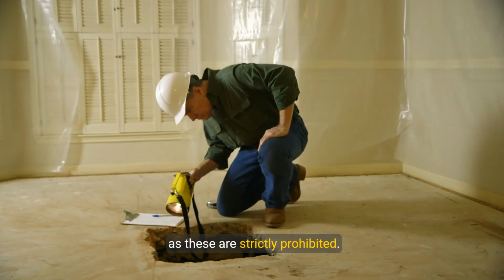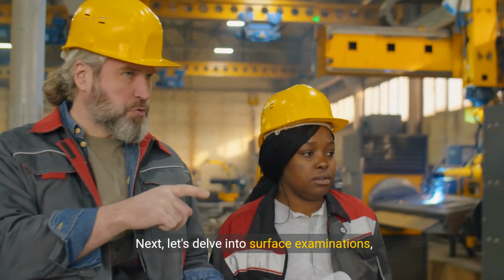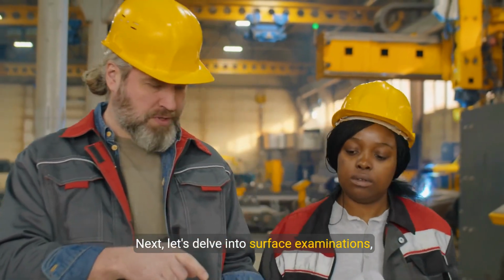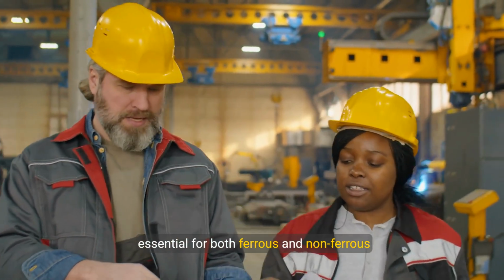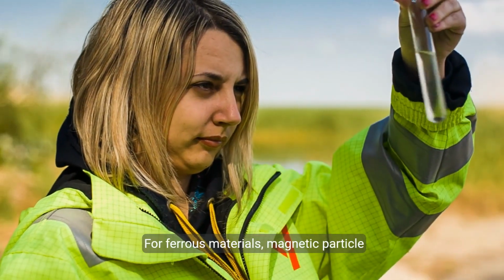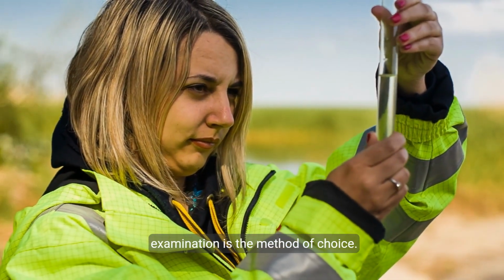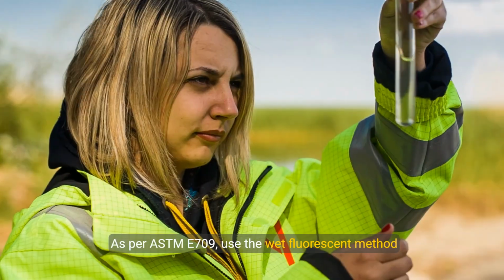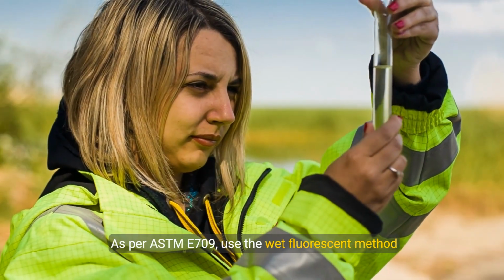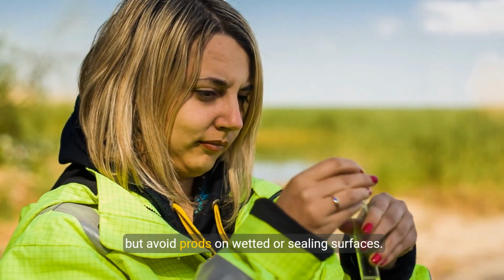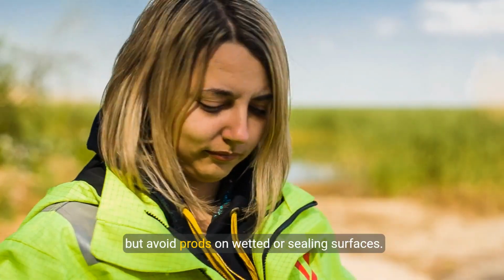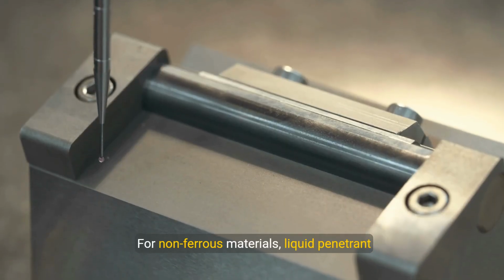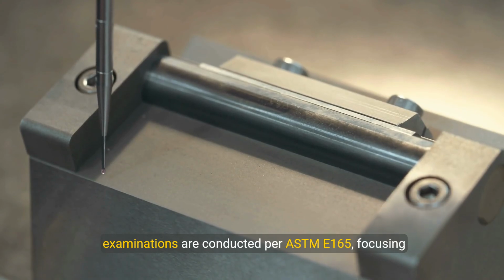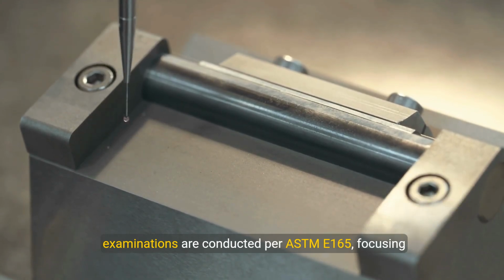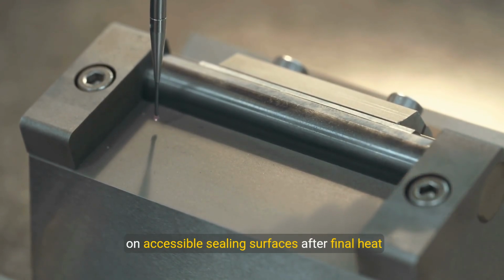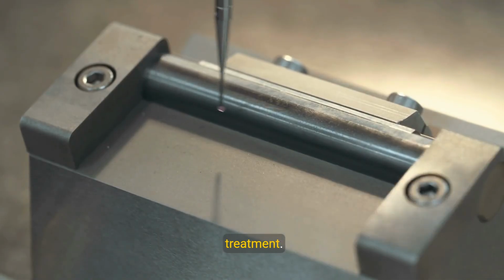these are strictly prohibited. Next, let's delve into surface examinations, essential for both ferrous and non-ferrous materials. For ferrous materials, magnetic particle examination is the method of choice. As per ASTM E709, use the wet fluorescent method, but avoid prods on wetted or sealing surfaces. For non-ferrous materials, liquid penetrant examinations are conducted per ASTM E165, focusing on accessible sealing surfaces after final heat treatment.